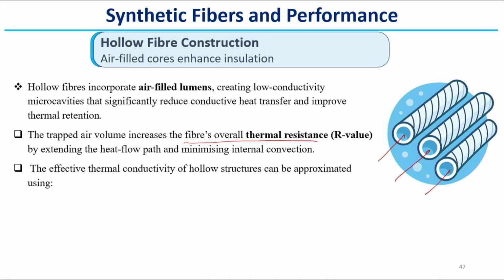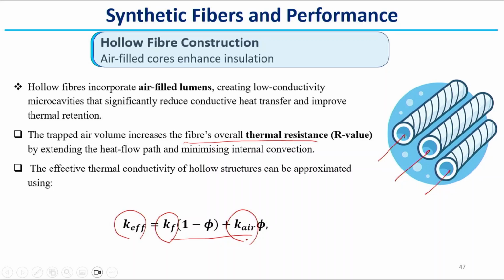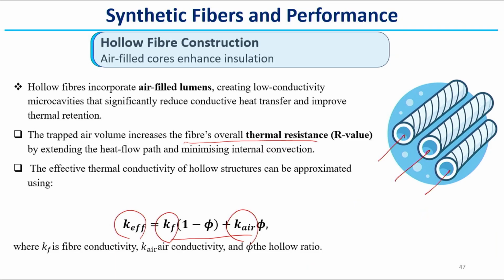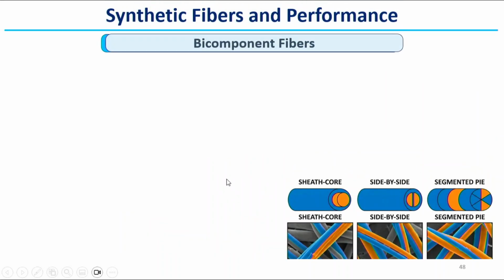The effective thermal conductivity of a hollow structure can be approximated by this formula. So, K effective, and this is the fiber's conductivity and air's conductivity. Depending on the porosity, phi is the hollow ratio. So, if the hollow ratio increases, then the effective thermal conductivity changes, you can see that. So, here we can control the thermal conductivity by controlling the hollow ratio.